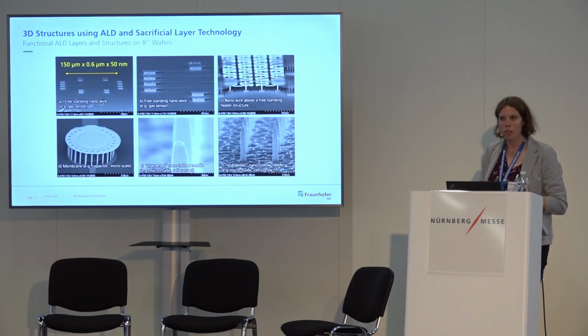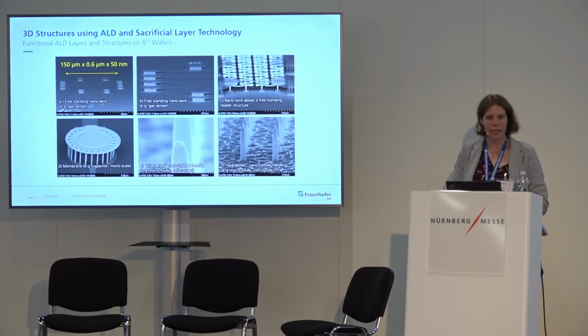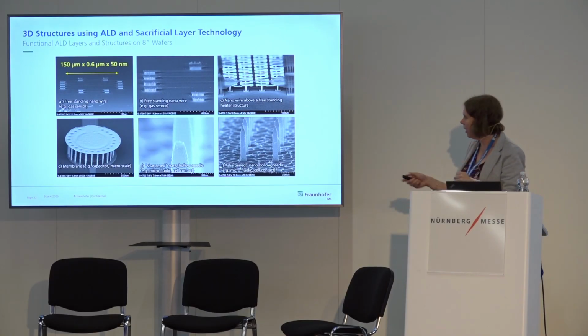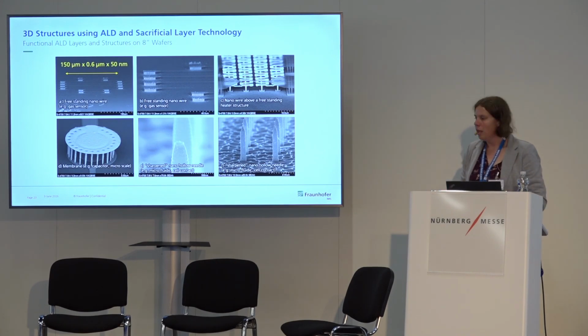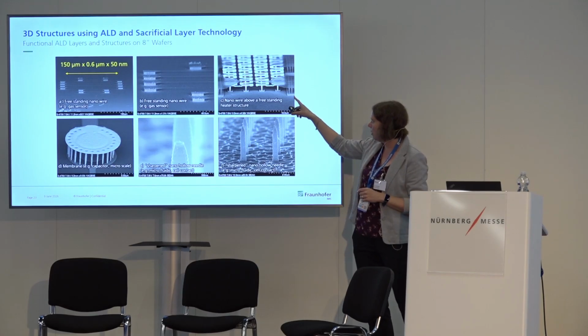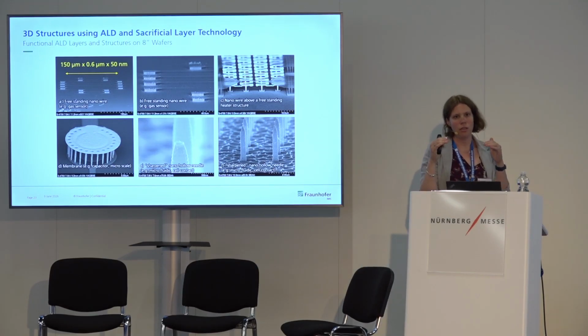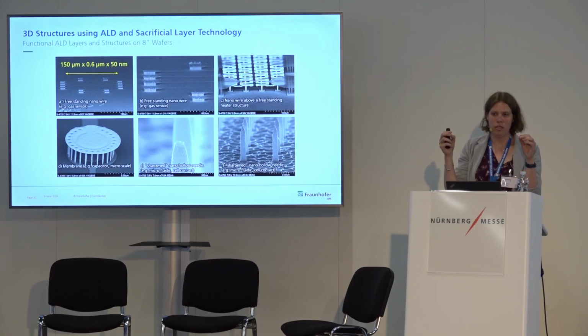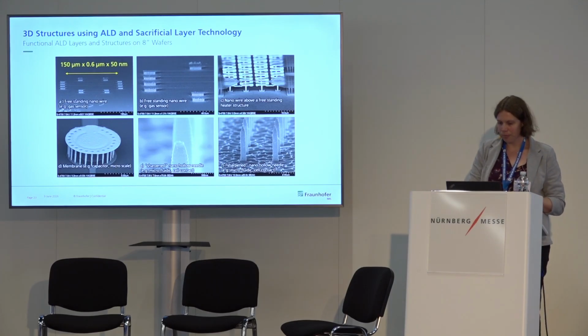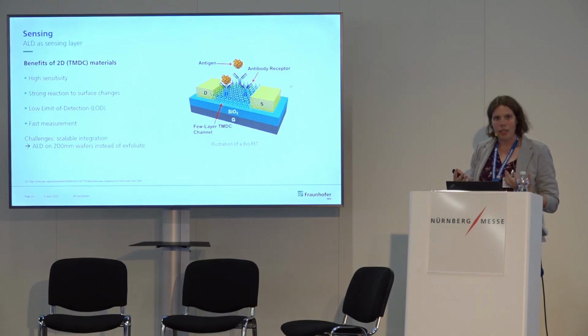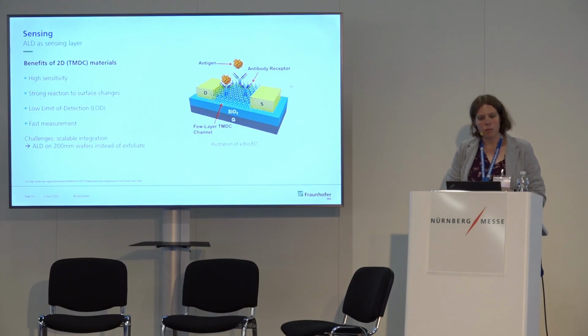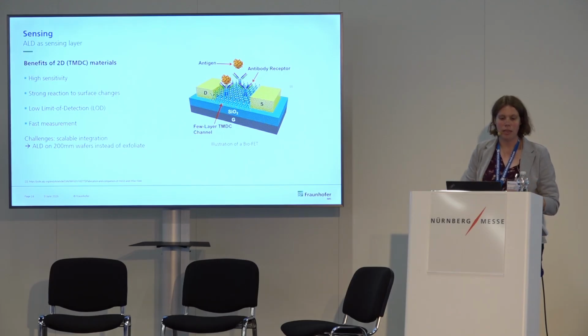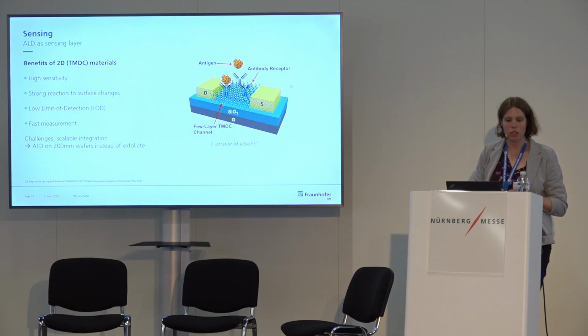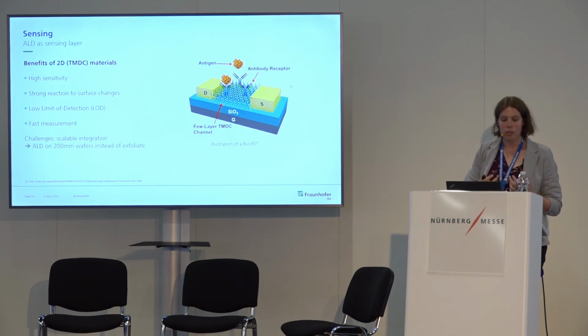Here are some pictures of what we have designed with this sacrificial layer etching. Here on the top there are the gas sensors, and here it was also used in a double way. So we have a freestanding heater structure, and above this freestanding heater structure we had this freestanding nanowire. With ALD, we have also the chance to deposit 2D materials. So the benefits are the high sensitivity, the strong reaction to surface change, the low limit of detection. So we can detect really, really small parts of biological material, and the fast measurement.